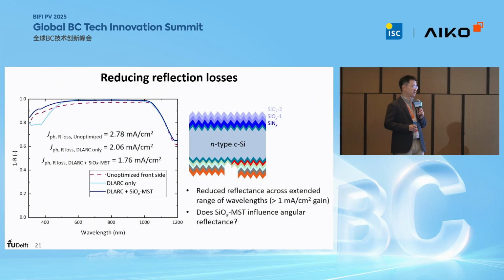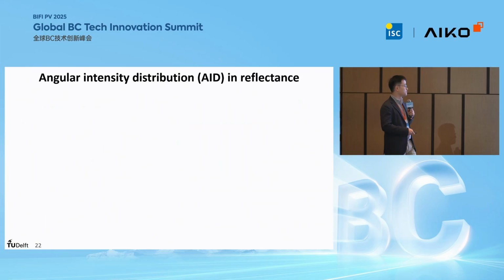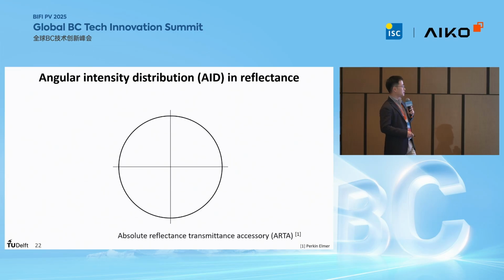With this structure of such a modulated surface texturing, we were also wondering if this surface morphology also affects the angular reflectance of such structure. So with this, we applied angular intensity distribution measurement in reflectance. Here, you have incoming light, and then you also have a moving detector. Basically, we place the sample by tilting at the proper angle. Then you can use the detector to detect the perpendicular reflectance and up to the parallel reflectance from the substrate, with a varying angle. And with this, we will show later the measurements of the reflectance varying from 0 degrees to 90 degrees.